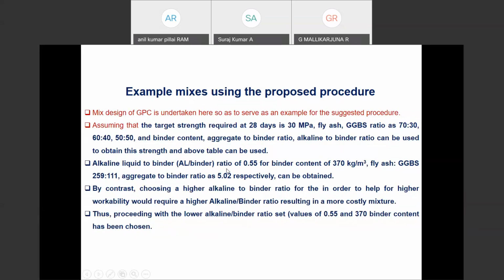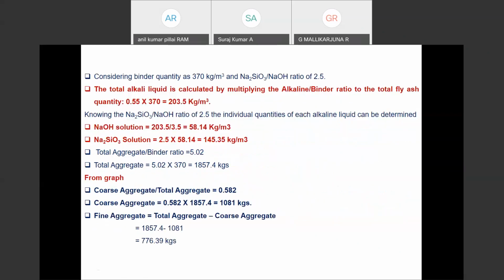Here the alkaline to binder ratio I have chosen as 0.55 and the binder content as 370, and fly ash switch, if we are going to go with 370 kg per meter cube, we can divide that fly ash with 259 and GGBS as 111, and aggregate ratio you can get as 5.02. Based on your required strength, you can select the values.